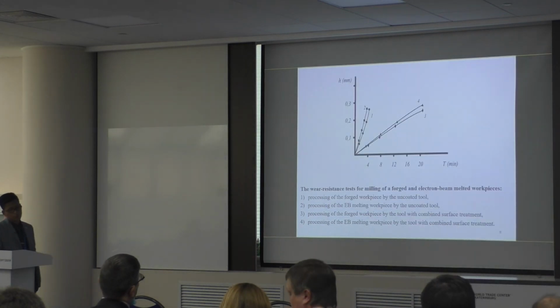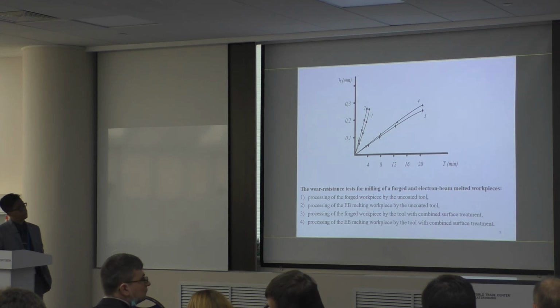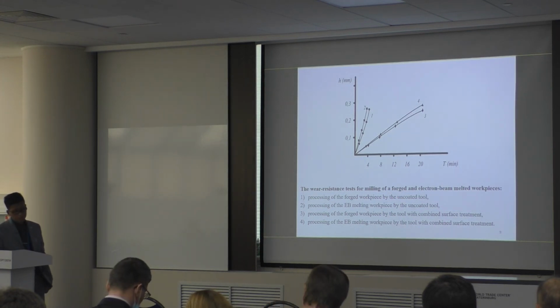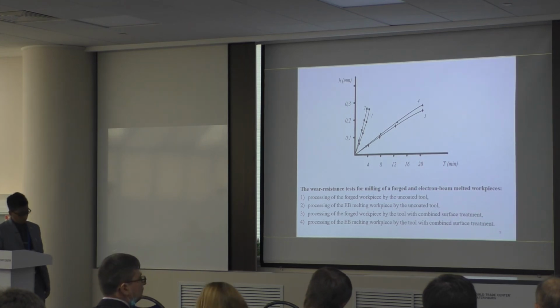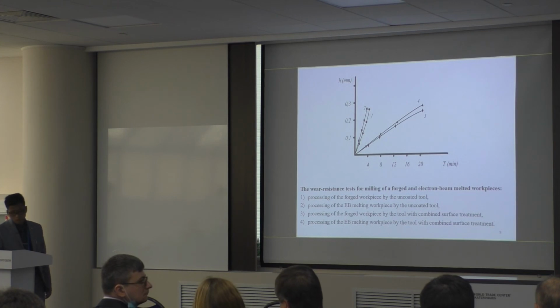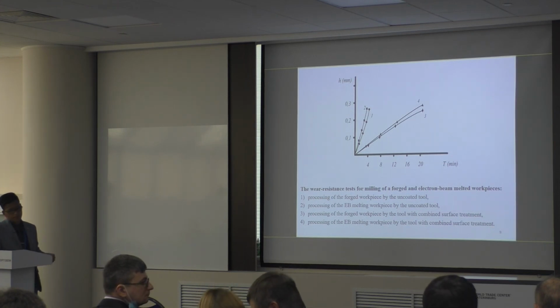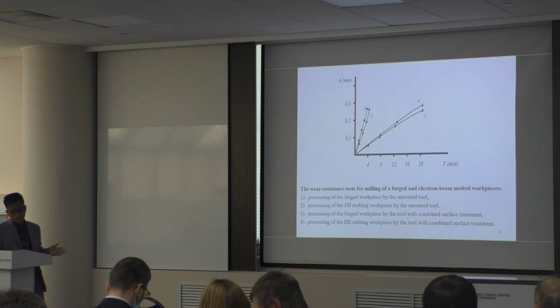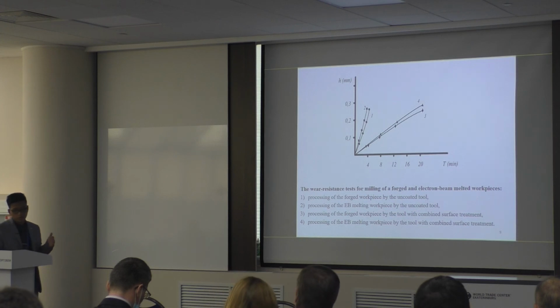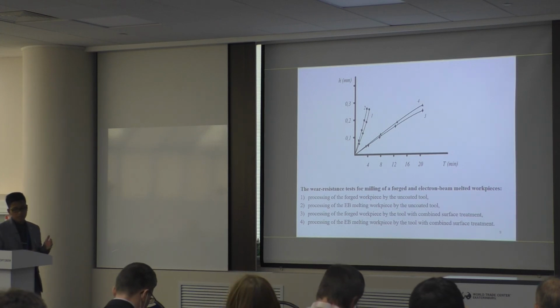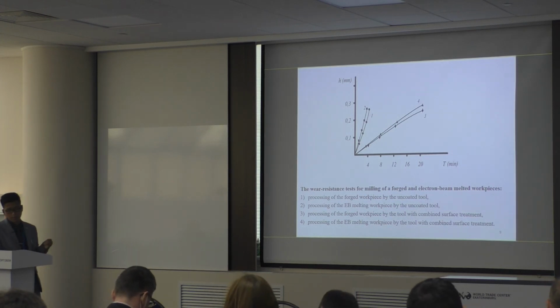The slide shows the result of the wear resistance test when milling a forged and electron-beam melted workpiece. The amount of wear on the rear surface of 0.2 millimeter is selected as the wear criterion. It is shown that the use of complex surface treatment made it possible to increase the tool life during milling in the specified mode up to 6 times.